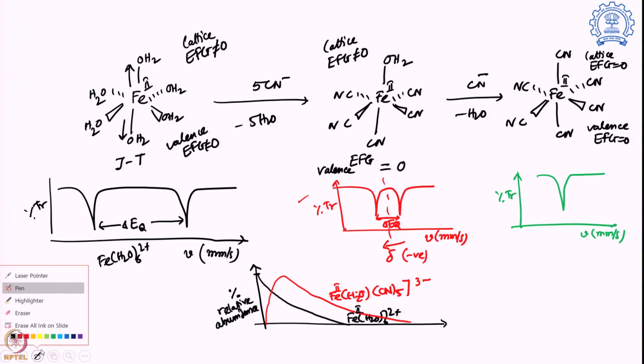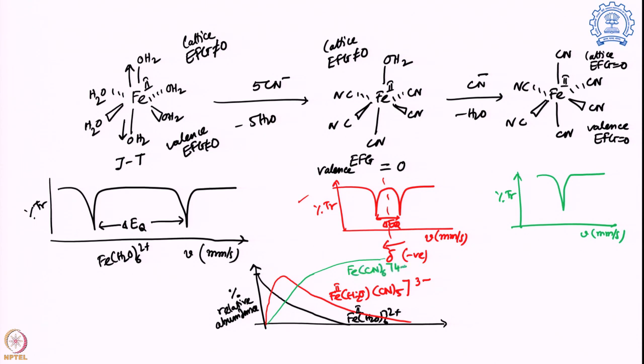And the final one is this green one, which actually comes into the picture much later, and then it slowly tries to be there, and at one point of time it will cease and 100% is reached. And this is the Fe(CN)6 4- charge over there. So by that you can see, you can follow the kinetics of the reaction very nicely with Mössbauer spectroscopy.